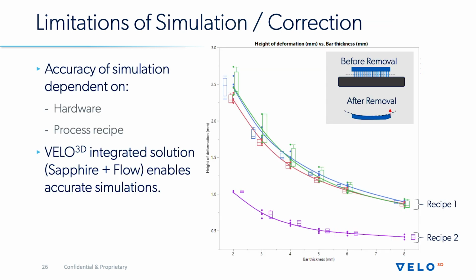The last thing I want to focus on before ending is that there are some limitations to these types of simulation approaches that we've had to work through. One of them is that the accuracy of the simulation is highly dependent on what hardware you're using to do the print and also what exact parameter set you're using. So to show that, on the right-hand side here, I've got a very simple experiment where you're printing horizontal bars, which are supported to the build plate. And in this case, you're just changing the thickness of how thick of a bar you're printing. As you thicken the bar, it ends up displacing less because the object becomes stiffer. So you get this characteristic downward shape in terms of the deformation versus how thick the bar is.